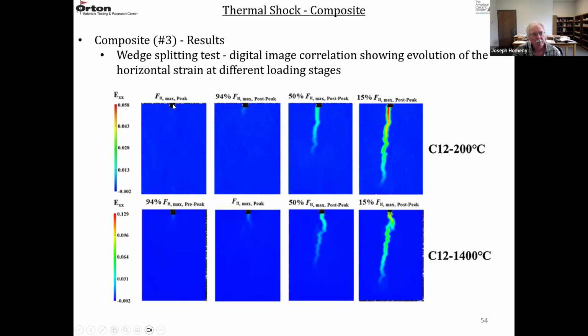So this is the horizontal force at the peak, and then right after the peak, you can see the crack is starting to grow. This is 50% after the maximum load. You have crack propagation, and then this is down to 15% post-peak, 15% of the horizontal force, and you can see the crack. And that was at 200 degrees C. This is at 1400 degrees C. And you can see the crack path is kind of tortuous. It's not linear at all.